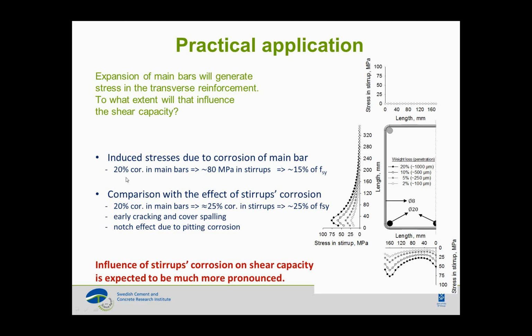So if we look into about 20% corrosion in the main bar, that induces stresses in the stirrup, in this case about 80 MPa, which is about 15% of the yield strength of your stirrup, right? But what if we look at a case where we have 20% of corrosion on the main bar, and then you have your stirrup there, and that is translated to about 25% corrosion on the stirrups, and that means you are losing about 25% of the cross section, or you have to decrease the yield strength of your stirrups by about 25%.